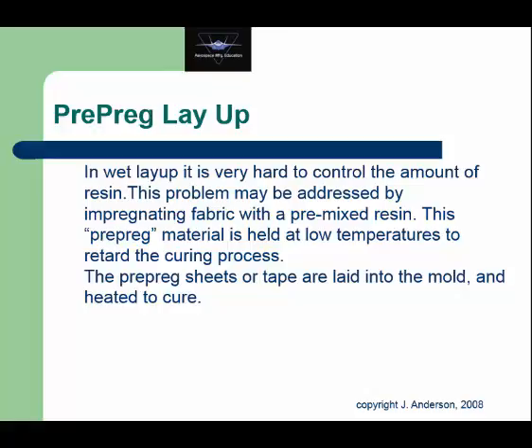For the highest performance parts, what we'd like to do is have the minimum amount of matrix material necessary to hold the fibers in place. The resin or the matrix material has a much lower strength than the fiber, so we want to have most of the weight of our part be fibers and a minimal amount of resin to hold it in place. We also want to put just enough resin in place in order to make the part. We don't want to waste any resin. So you can see from the video and the description we've had, the wet layup process is not very economical in terms of resin. A solution to this is to have a pre-preg material.